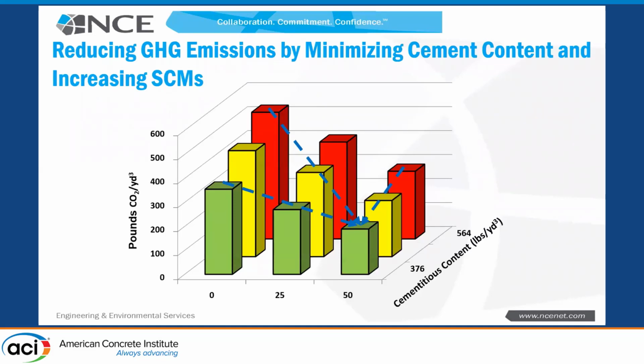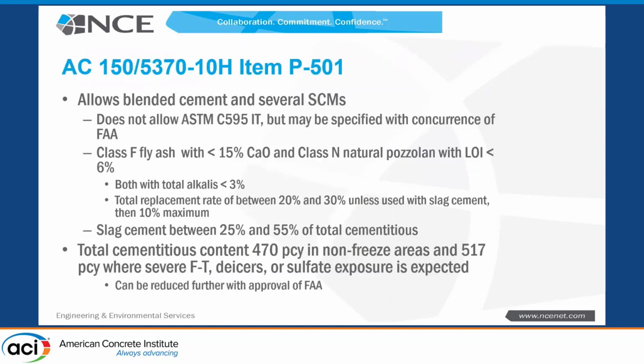The general trend here, the way to think about it, is to go away from your pure Portland mixes, reduce your cement content, and at the same time try to replace clinker with SCMs. If you look at the current P501, it actually allows you to do a lot of things. It does not allow 1Ts, but it does allow all of the other blended cements, including 1Ls. The military does not allow 1L at this point, I don't believe. That's what Peter was talking about. They're the ones still having heartburn. Last ones.